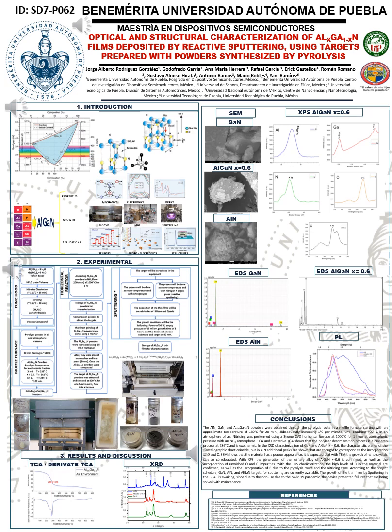Due to their emission energies, with wavelengths from the blue band to the ultraviolet band, 470 nanometers to 300 nanometers. GaN, AlGaN, and InN compounds generally crystallize in the stable phase as wurtzite structure and the metastable phase as zincblende, with a wide band gap, and values of 0.79 electron volts for InN, 3.4 electron volts for GaN, and 6.2 electron volts for AlN.